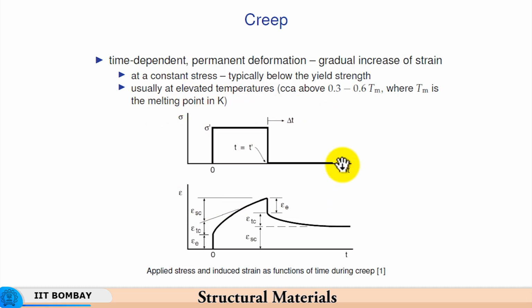So, creep is basically a phenomenon that occurs below the yield strength. You might not have stressed the material beyond the yield strength, but the mechanisms which operate are time, temperature and activation energy dependent. Basically, diffusion is the rate controlling mechanism. So, it has nothing to do really with dislocation movement. Yielding occurs when the dislocations just start moving, but here there is nothing like dislocation movement. The creep will take place purely governed by diffusion. So, that is where the strain can occur even below the yield strength of the material.